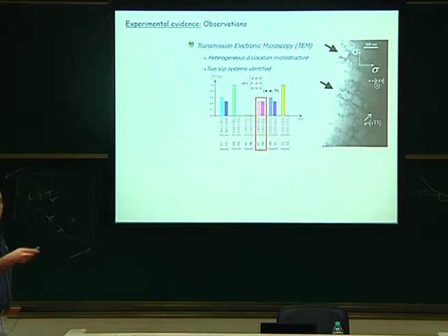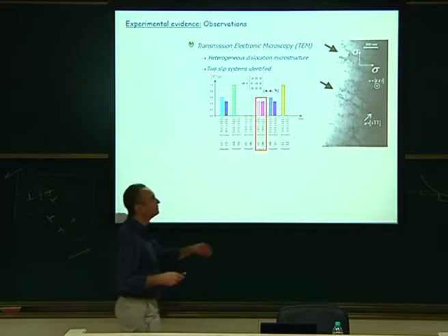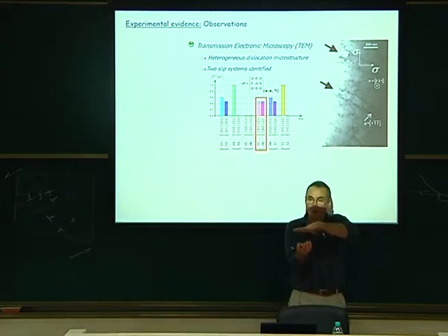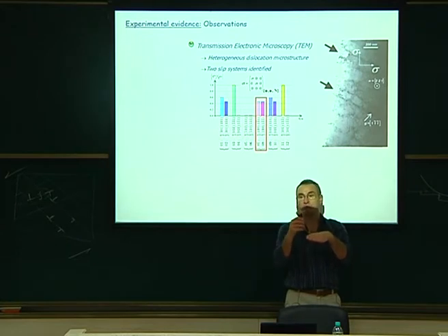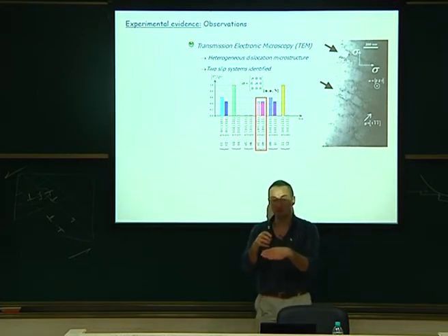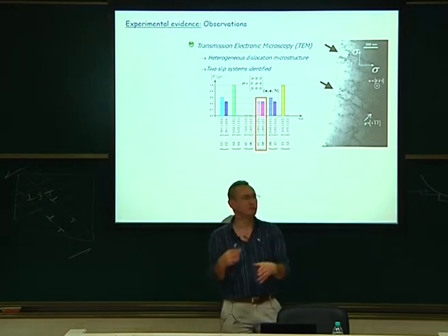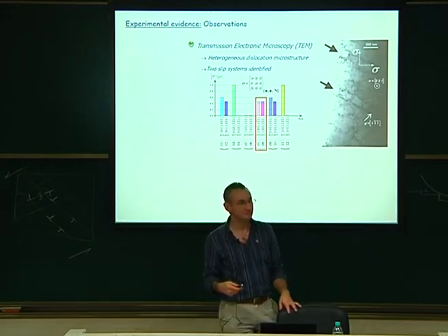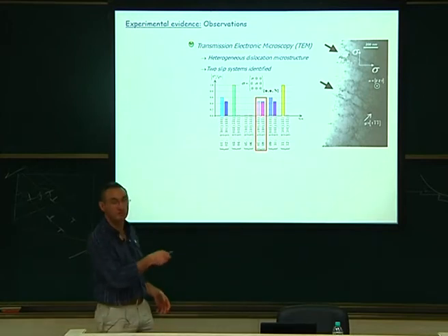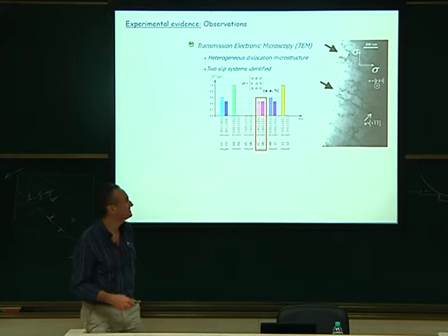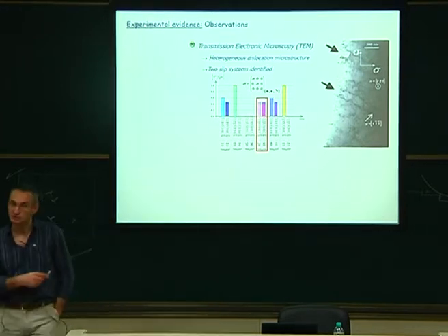Oh, so Professor Sundaraman explained this last time. To recognize the character of the dislocations, you need to look at one single dislocation, rotate your specimen so that you distinguish your dislocation with g, the diffraction orientation. When g.b equals 0, you know that you are in certain conditions. You have to do that for all orientations, and with, I think, 4 pictures. Okay, so it's a long job. It's a 1-day analysis for a single picture like that. It's very long. But at the end of the day, he got this information, which is very important for us.